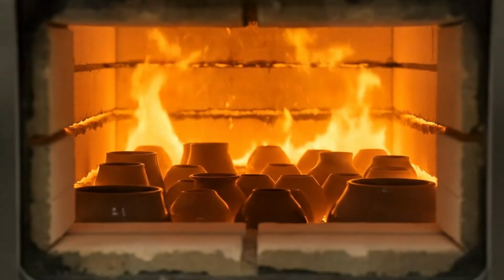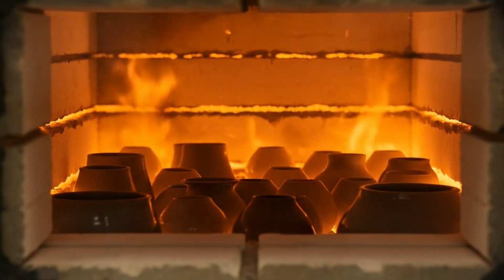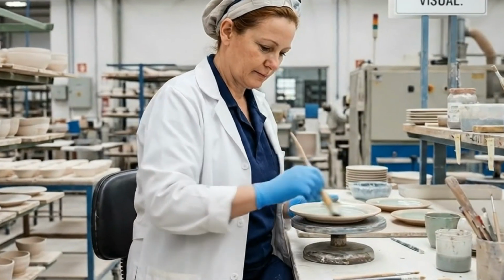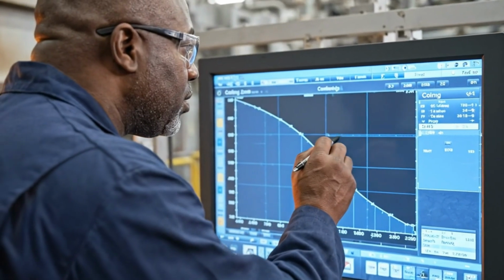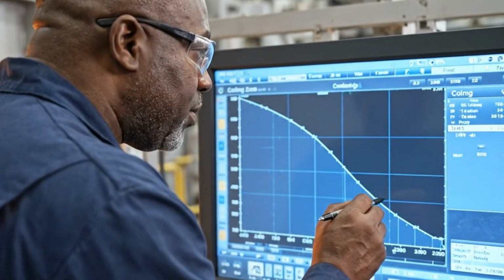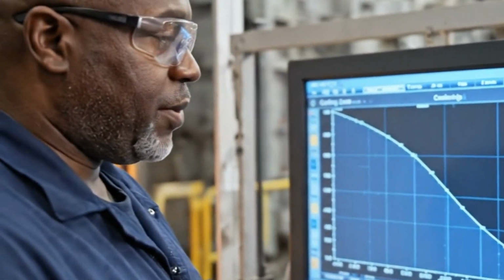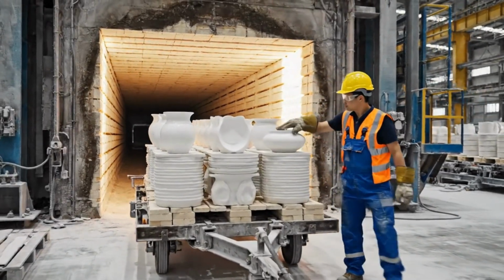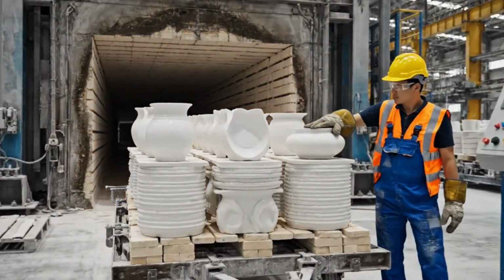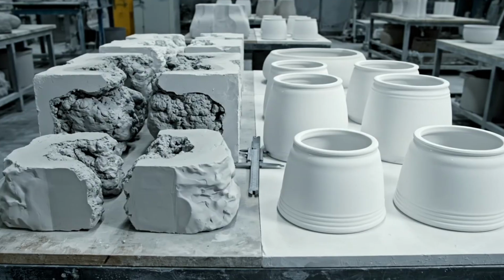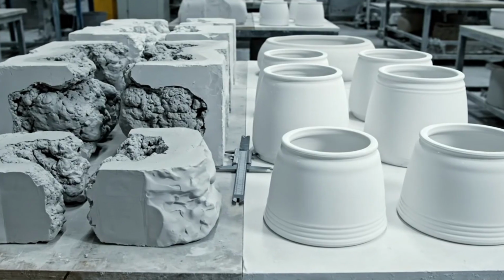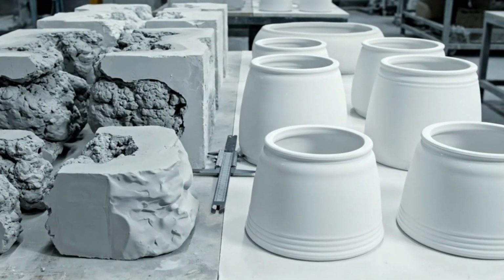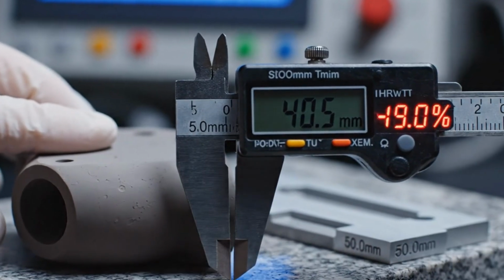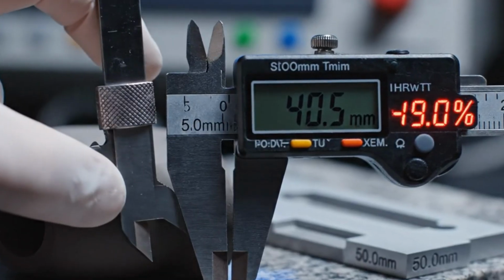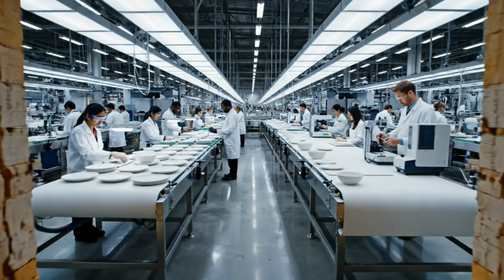As the pieces travel through the cooling zone at the end of the tunnel kiln, the temperature drops slowly and precisely. Too fast, and the glass phase would freeze with internal stresses that would cause immediate or delayed cracking. The cooling curve is engineered with the same precision as the firing curve. When the pieces finally emerge from the end of the tunnel, they are cool enough to handle, transformed from fragile earth into dense, vitrified ceramic, and they have shrunk again. Another 8 to 10%. Combined with the drying shrinkage, the finished piece is approximately 15 to 20% smaller than the original mold. The mold was designed for this. Everything was designed for this.